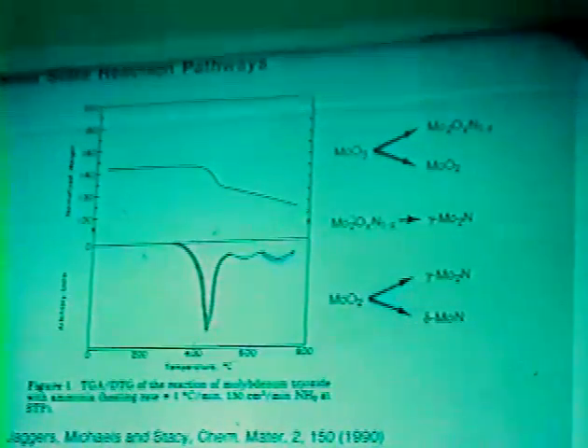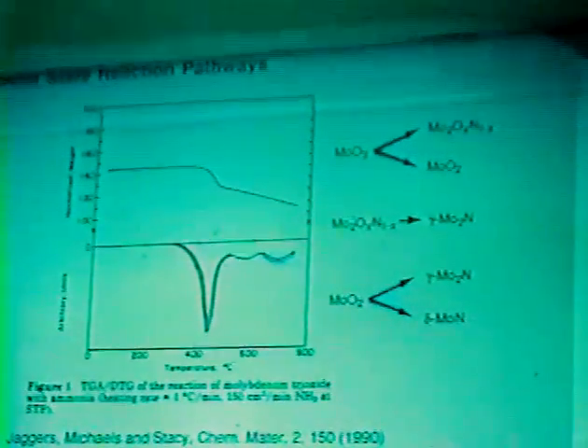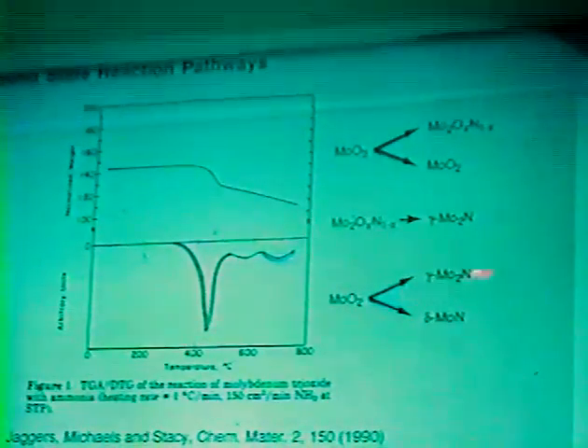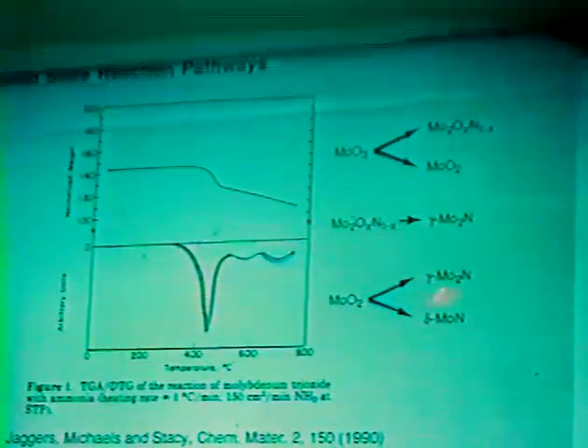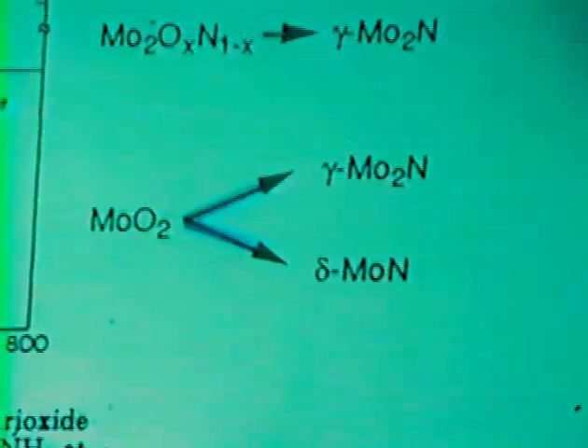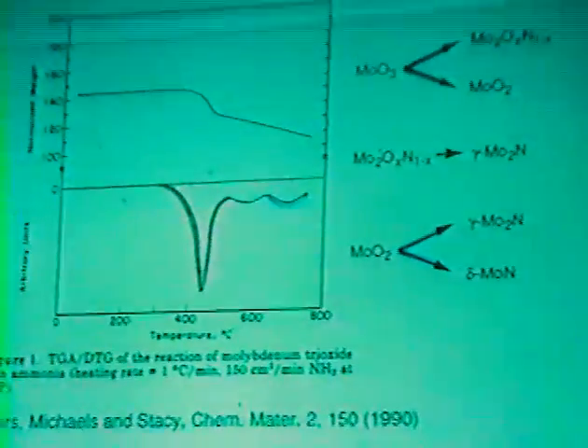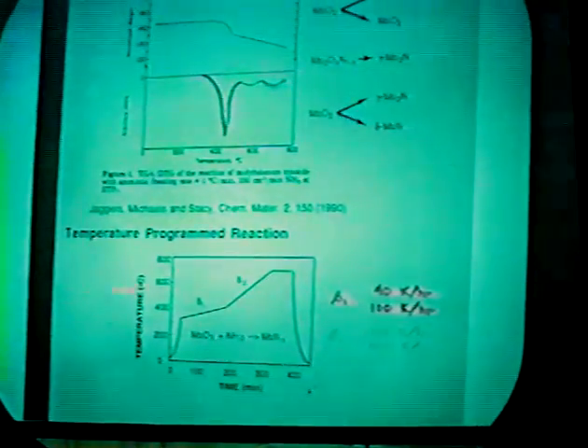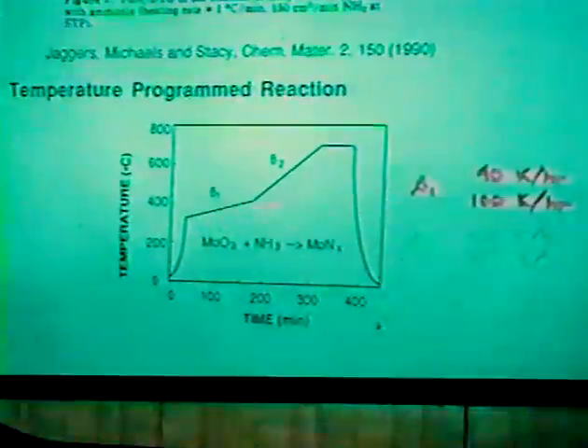You'll notice that there are three regimes. There's this red regime here, during which moly trioxide in the presence of ammonia is converted into an oxynitride and dioxide. Subsequently, and it's kind of hard to see, but the oxynitride can be converted into the nitride at temperatures between about 500 and 600 degrees C. The dioxide can then convert into the gamma phase of the nitride or the delta phase of the nitride. You'll remember that the gamma phase is FCC and the delta phase is hexagonal.